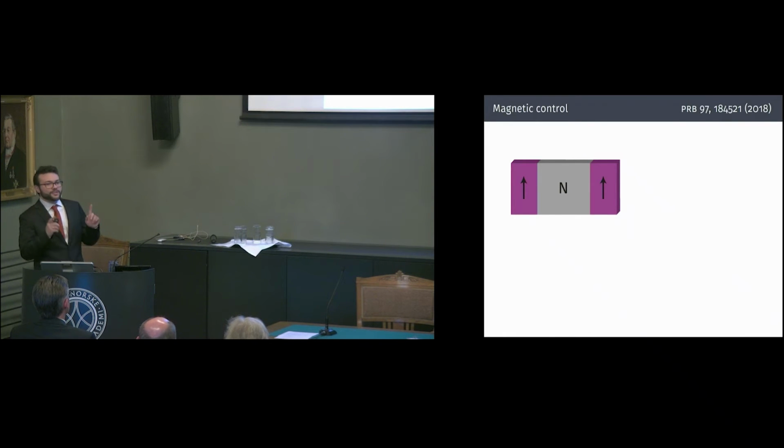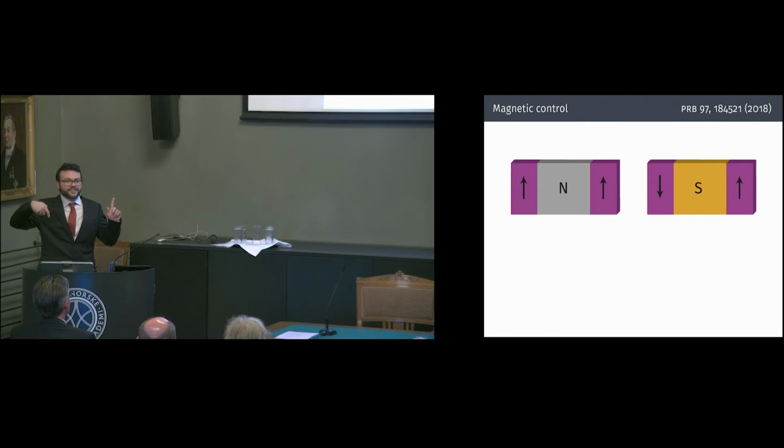However, if you manage to twist one of the magnets to point in the other direction, then actually the two magnetic fields cancel out near the center of the superconductor, and then superconductivity is restored. So this is not a new idea. This was proposed in the 60s and has been done experimentally for at least 20 years. But it's known as a superconducting spin valve.